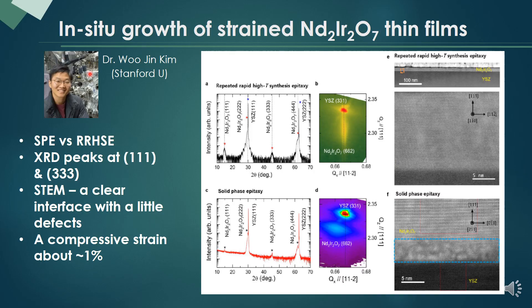With the work of Dr. Woojin Kim, we can grow the strained Nd2Ir2O7 thin film. Here is the data. In this XRD data and TEM data, we can see a clear interface between the substrate and Nd2Ir2O7 thin film.